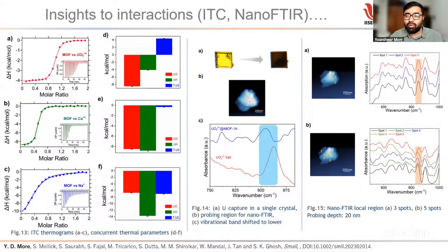It exactly uses thermodynamics, that is the enthalpy and entropy change as well as the free energy change operating in the reaction. So what we did here, we gave doses of uranium into the MOF solution, and we identified this thermodynamics. So what is happening when the MOF is treated with uranyl cation at nanomolar concentration? You can see here the resultant data shows delta G is decreasing. Delta G is the free energy. If the free energy is decreasing, it means the reaction is favorable. It means uranium going within the pore is a favorable interaction. Whereas T delta S, that is the entropy factor, is also increasing, but delta H is decreasing.